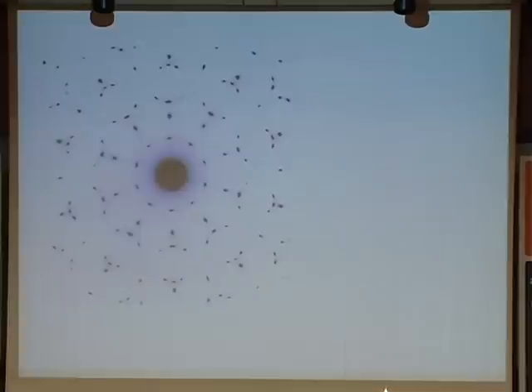What you see here are 10 crystals, but they are twin related. That means that this crystal is twin related to this, and this is twin related to this, and this is twin related to this, and so on. And in between each two, you have a twin boundary. Now, if you take a diffraction pattern from one of them, then you have a regular periodic diffraction pattern. But if you take a diffraction pattern from all of them together, then you have 10 superimposed diffraction patterns, 36 degrees from each other, and this superposition has a 10-fold rotational symmetry, of course. And this is how it looks. This diffraction pattern was taken from the crystal that I've just shown you when I took a diffraction pattern from all of them together. And this has, seemingly, a 10-fold rotational symmetry.